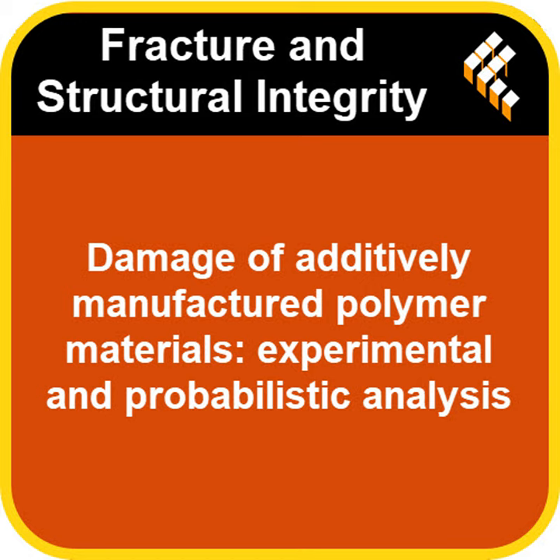Got it. And they saw a significant reduction in the material's remaining strength, both the elastic limit, where it starts to deform permanently, and the ultimate stress, the breaking point, as this life fraction increased. So more crack means less strength left. Pretty much. It confirms that as a crack grows relative to the part size, the material gets progressively weaker and also tends to fail more abruptly, becoming more brittle. And they actually mapped out this damage progression based on that life fraction, didn't they? Identified stages. They did. There were 3 stages observed experimentally, looking at how damage accumulated.